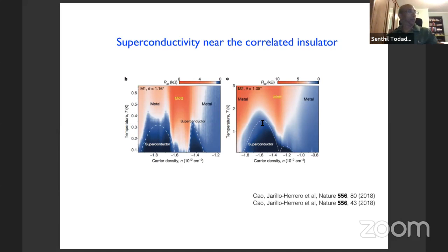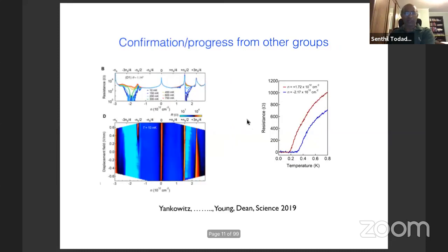Okay, so this was interesting. It was a very unusual platform to see such phenomena, and these experiments were quickly reproduced by other groups. So here's data from the group of Andrea Young and Corey Dean, or rather, they are combined groups. So there's various things in this plot, but overall, the message is that yes, indeed, the phenomena that were reported earlier, they saw it too, and they saw other features, like, for instance, superconductivity on the electron dope side of neutrality.